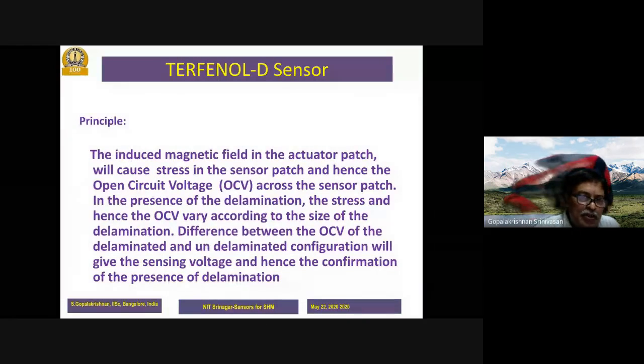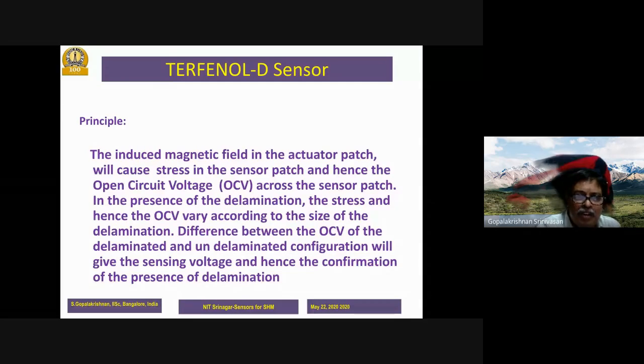So once we actually got this model, we wanted to test it experimentally. So we bought these Terfenol rods, we powdered them in an inert atmosphere, we mixed with epoxy, we created a magnetostrictive patch, and then embedded them in an 8-ply laminate composite. And then we induced the damages, and we wanted to find whether our model gives exact results.